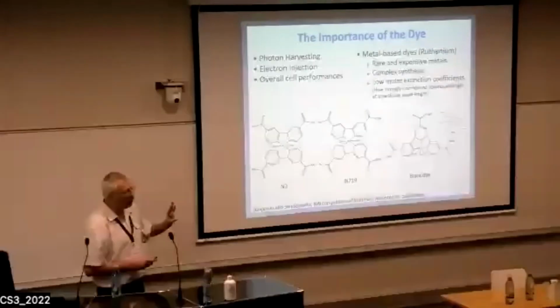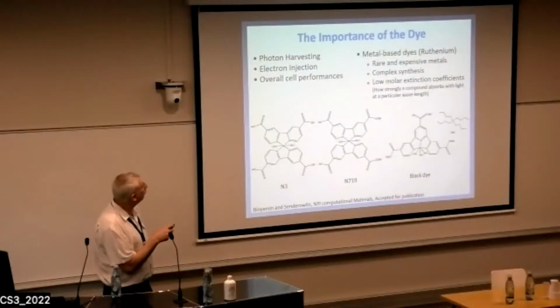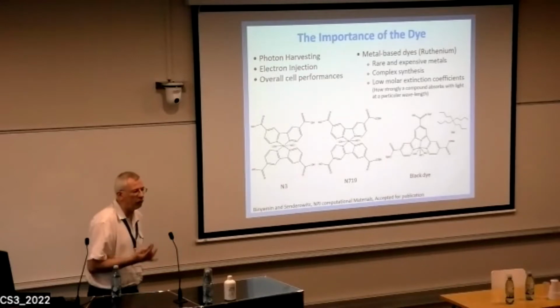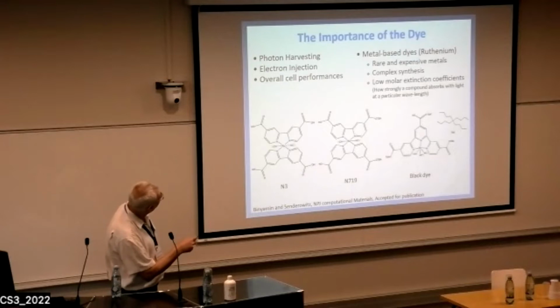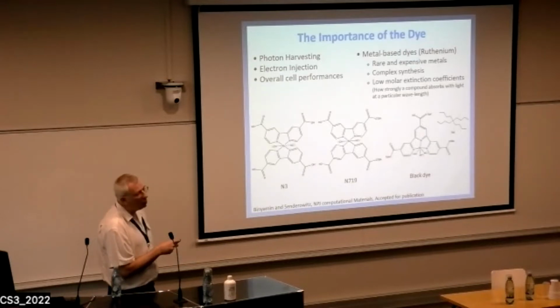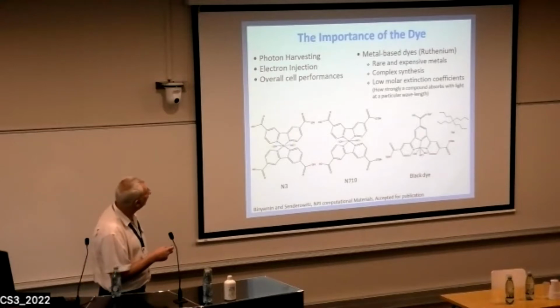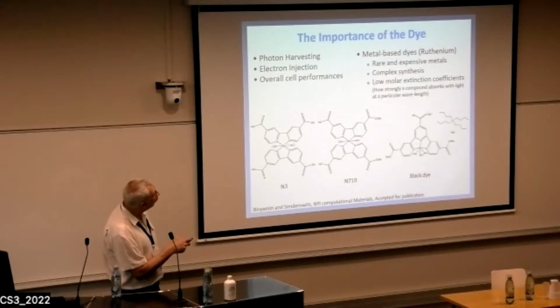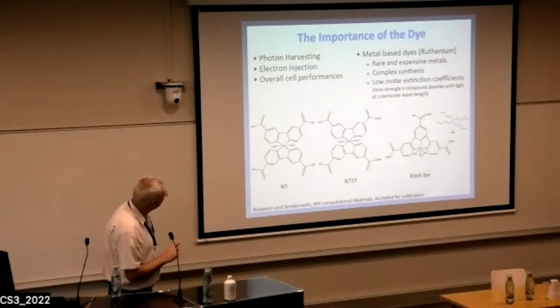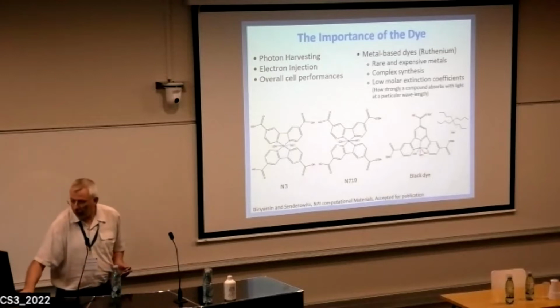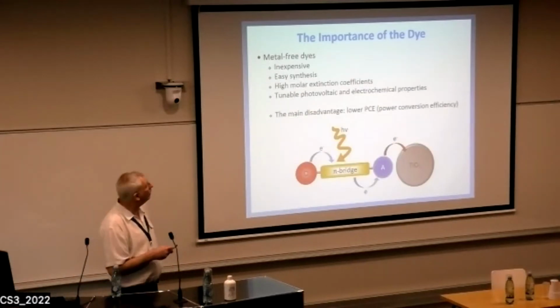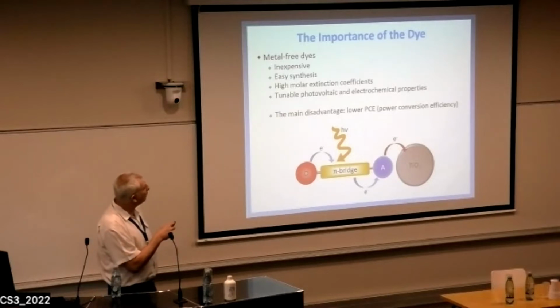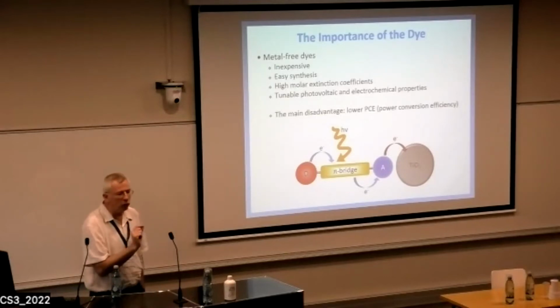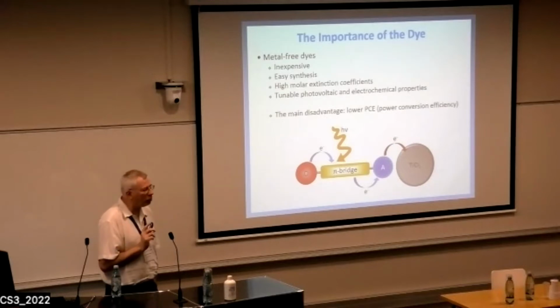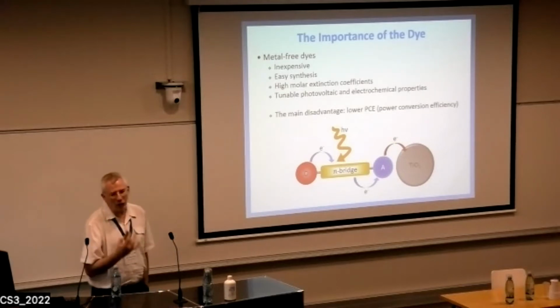Now, the dye is critical in these cells because it is responsible for photon harvesting, electron injection, and overall cell performance. And people for years have been using metal-based dyes, usually ruthenium. The problem is that they're expensive. Ruthenium is an expensive metal. Synthesis is complex, and there's also a low molar extinction coefficient, which is explained here, but this is not that important. And understanding the deficiencies of these dyes, people have started to use metal-free dyes, which are inexpensive, easy to synthesize, with a high molar extinction coefficient. You can tune them, you can make small modifications which will change their properties. There's only one problem, a small problem. The PCE is not that great. The power conversion efficiency is not that great.